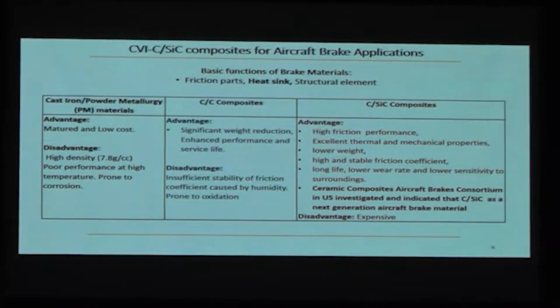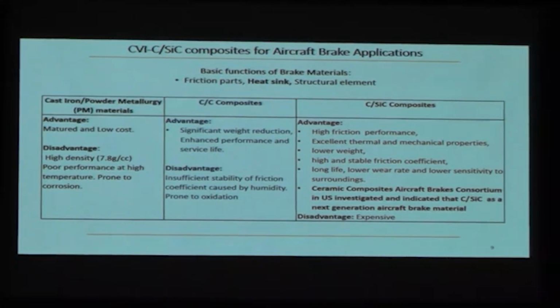So you all know the brake disc, starting from metal to CC, carbon-carbon composite. Recently, 4 or 5 years back, at the consortium met by the international community, the Aircraft Brake Disc Manufacturers Association declared that C/SiC composite is the next generation aircraft brake disc material, like a fourth generation material. So the advantage compared to the CC is very good. Almost all commercial aircraft today are flying with carbon-carbon, no problem. But there are some disadvantages, like instability in friction performance, the coefficient of friction, and also proneness to oxidation. Since the matrix is carbon, for some reason the friction dissipates more energy, and if it becomes more than 500, 600 degrees centigrade, the carbon will oxidize. So that is a drawback.